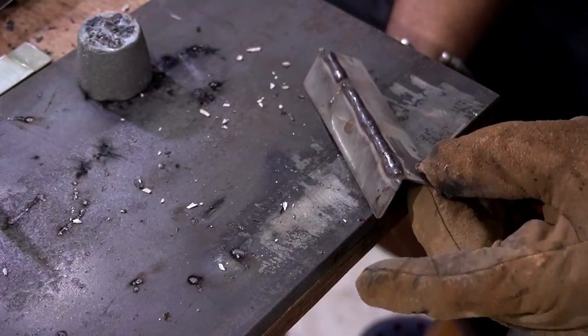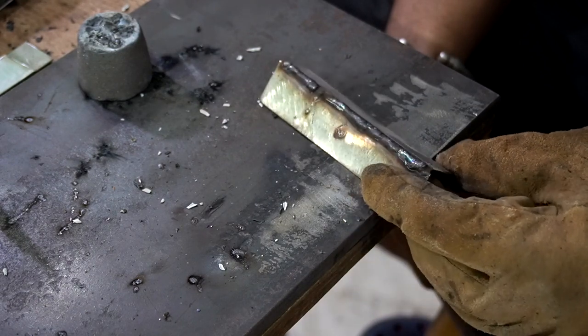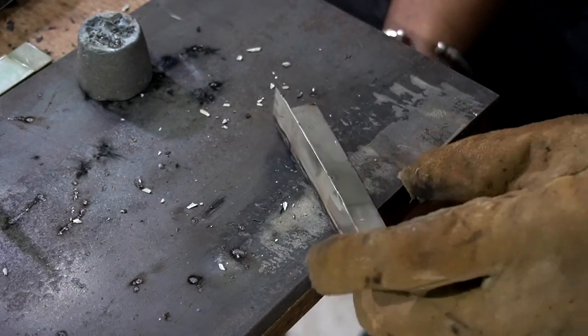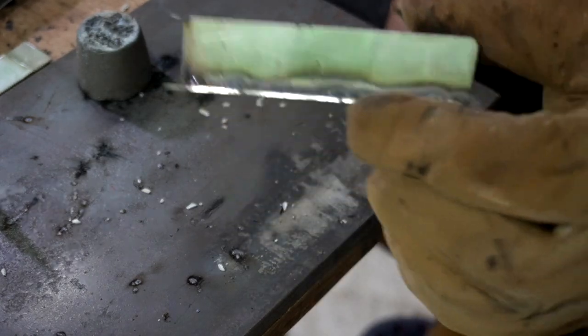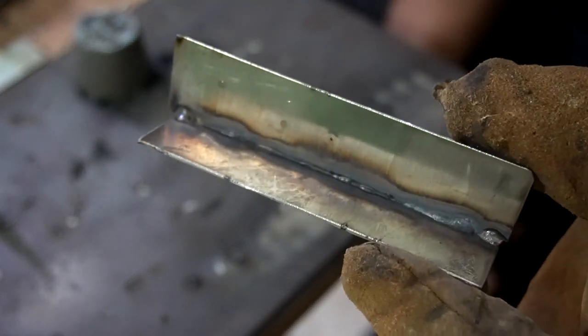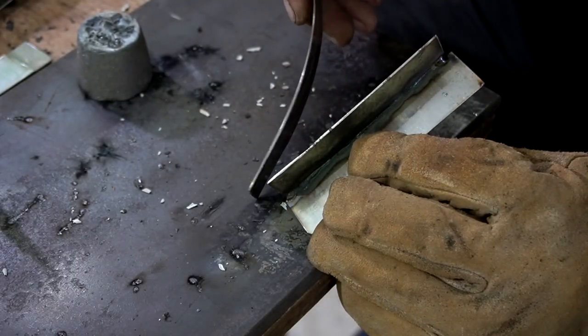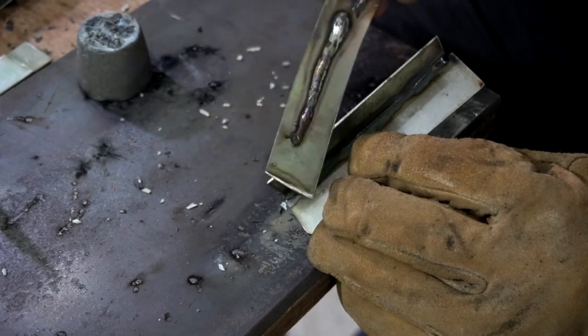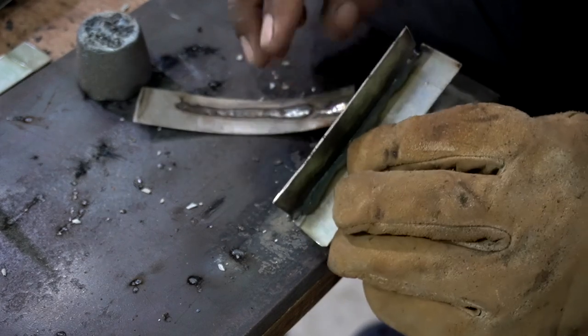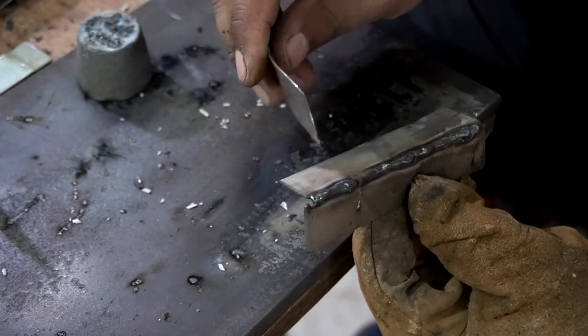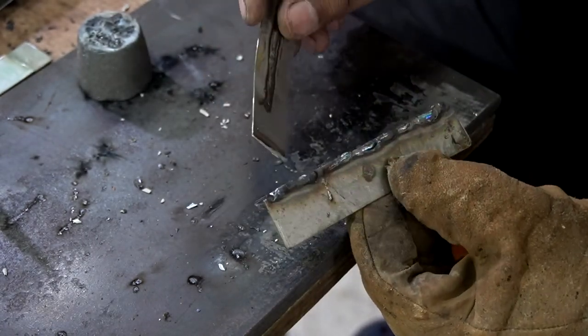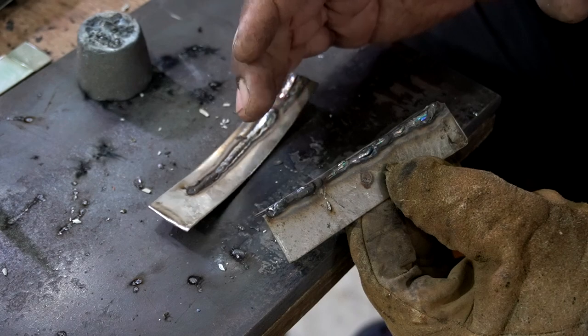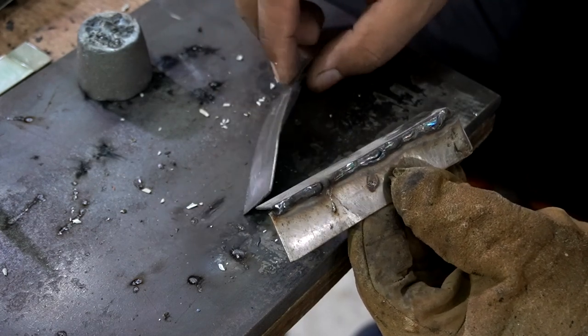So if you're considering the weld bead, it's not looking pretty, but there is a good fusion between the two surfaces, and if you compare the warping, then in the angle the warping is almost negligible compared to a straight weld. Surely the technique is quite effective, but you need a lot of practice to do that.